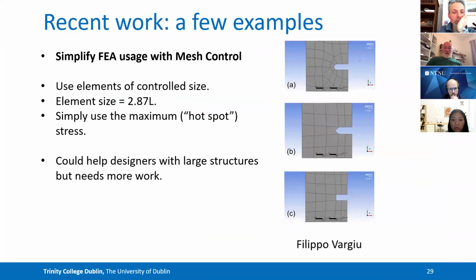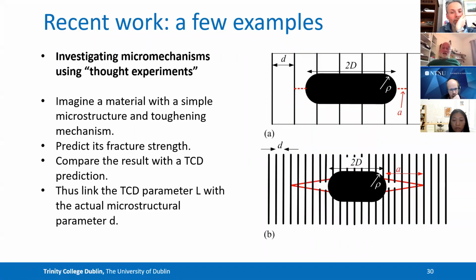Trying to find easier ways to make it easier for use in industry, where sometimes you don't want to make a very fine mesh to capture the stresses near a notch. Looking at this idea we call mesh control, which is to have quite a coarse mesh, but one with constant element size. You have to trick the program a little bit to do that. But it turns out that if you do that, you can often get good results just using the hotspot stress if you control the element size as a function of L, about 3 times L actually. So it's kind of like averaging over distance, similar to the critical distance. And this may make it easier for industrial designers looking at large and complex structures.